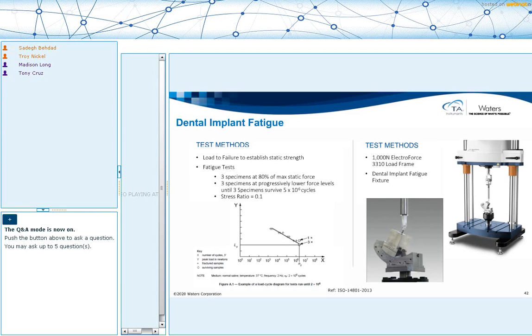And then it says the stress ratio should be 0.1, meaning that when you're oscillating that load, the minimum load to maximum load ratio is going to be, your minimum load is 1/10 of your maximum load.